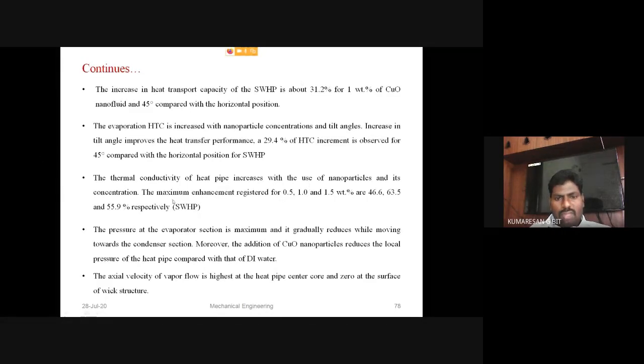Then the thermal conductivity of heat pipe increases with the use of nanoparticles and increasing the concentration. That maximum enhancement is registered for 1 weight percentage of nanofluid, and that value is 63.5%. Then the pressure at the evaporator section is maximum, and it gradually reduces while moving towards the condenser section. Moreover, the addition of copper oxide nanoparticles reduces the local pressure of the heat pipe compared with the base fluid.